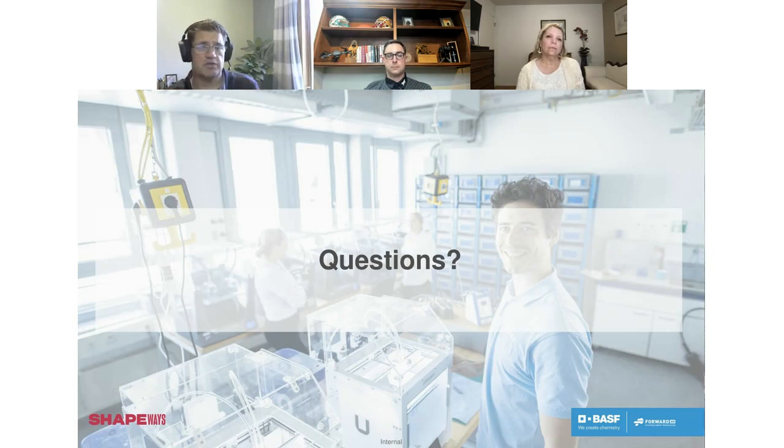As far as end use parts and finding ways to do a second life, we've done a series of studies around our TPU. It's kind of a theme we're talking about here today, because we've put a lot of effort and time into the TPU because we think thermoplastic urethane is going to have a lot of different potential applications: automotive, consumer, medical. There's just a lot there. So we've put some resources into finding a second life path for the TPU. What we've discovered is that BASF has injection molding grades of TPU, of course, and so our printable TPU finished parts can be added to regrind that's fed back into the injection molding process with our regular TPU.